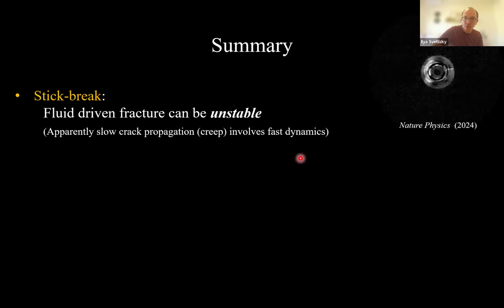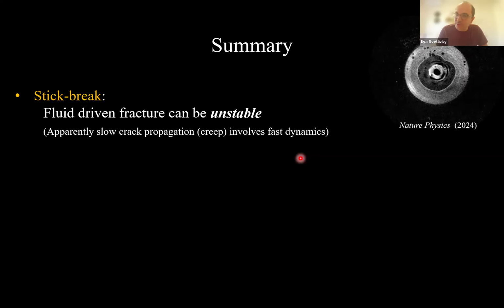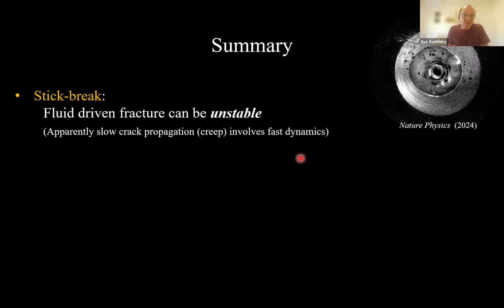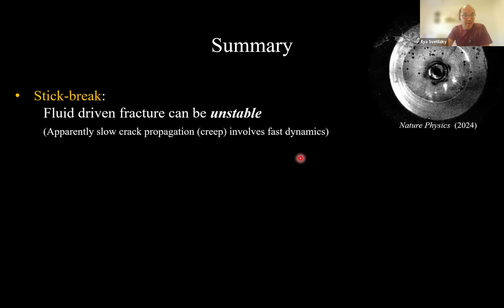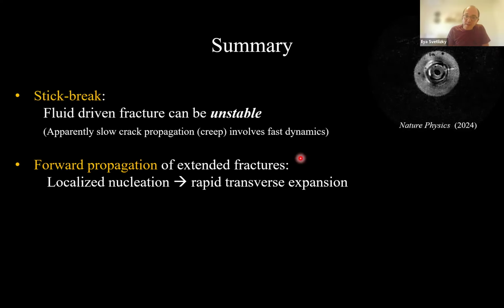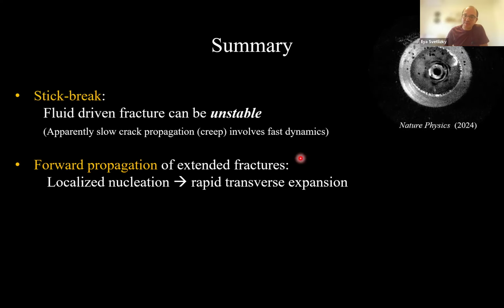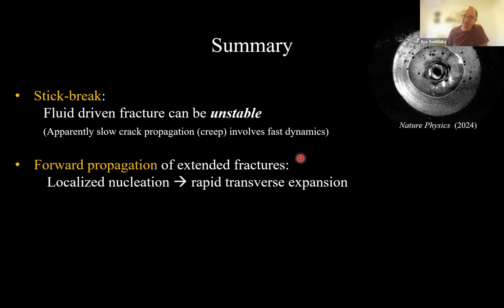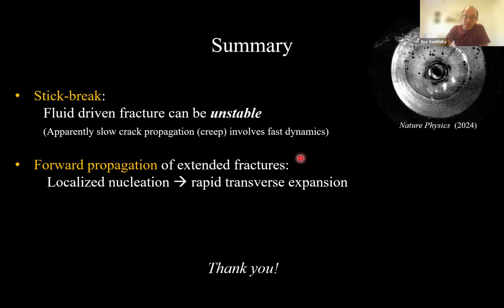So let me conclude. One of the surprising parts for us is that fluid-driven fracture can be unstable. To our understanding, this hasn't been explicitly said in the literature. So many of the times that you see a slowly propagating or creeping crack, it actually can involve very fast dynamics. The second point is that these dynamics take place through a very specific mechanism, where the radial expansion is nucleated in some localized region, and the circle expands by transverse cracks that run along the transverse direction. So thank you very much for your attention.